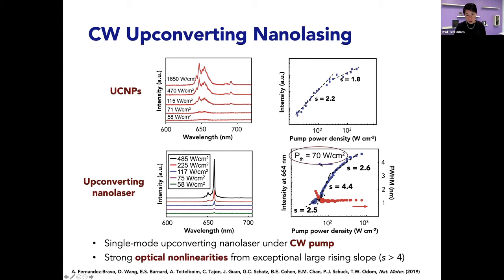But if we evaluate this threshold, and we have one that's even 3 or 4 times lower, this is already 2 orders of magnitude lower than semiconducting diodes, commercial semiconducting diodes. So this is quite nice. It's a little bit unexpected that it's so low, and that it can be excited under a continuous wave pump. The mechanism is quite interesting as well, but it indicates that even in these unconventional materials, we can start to achieve metrics that are important for translation.